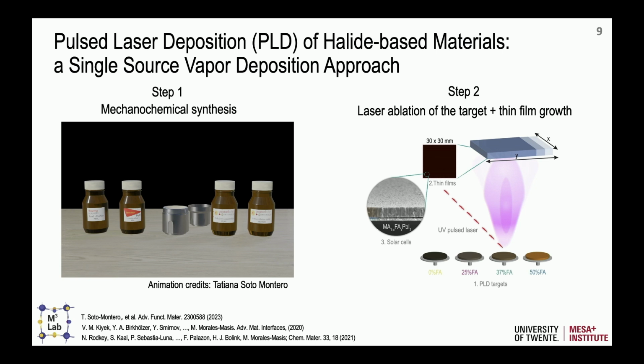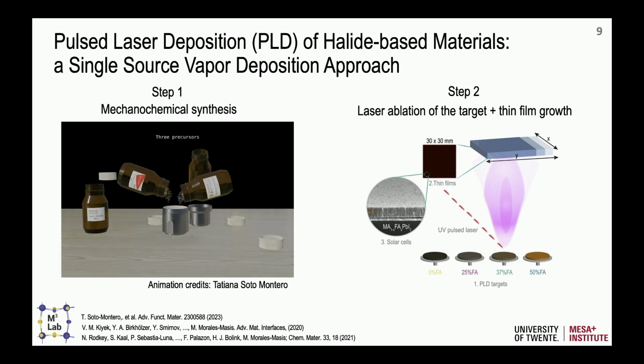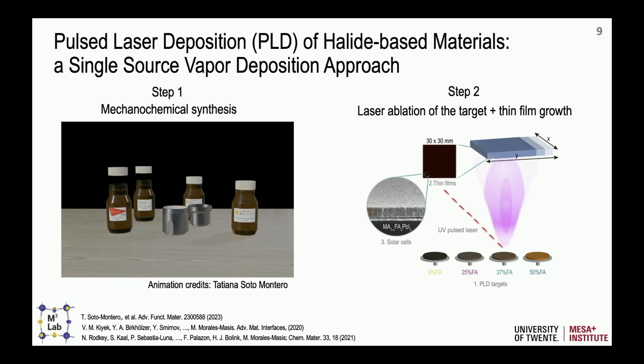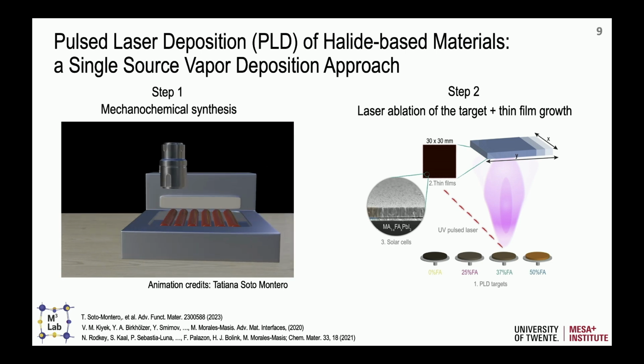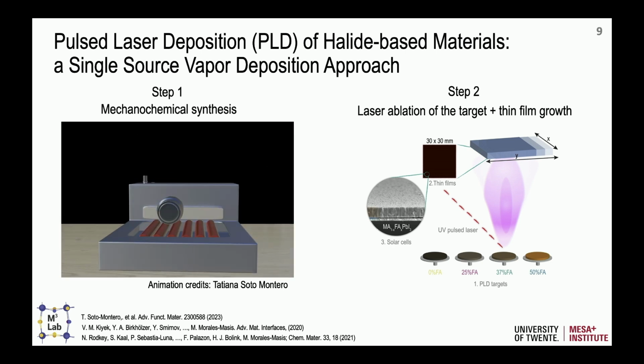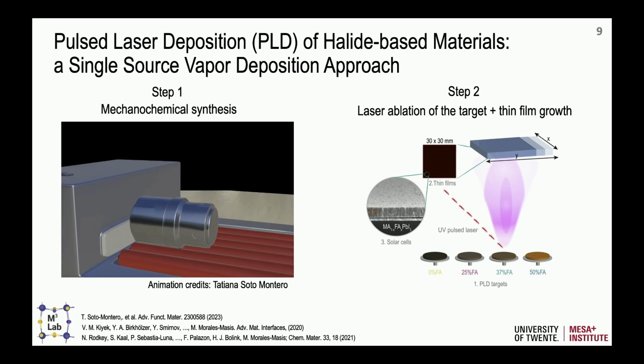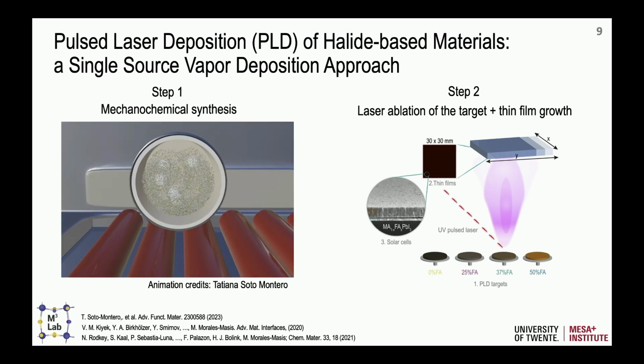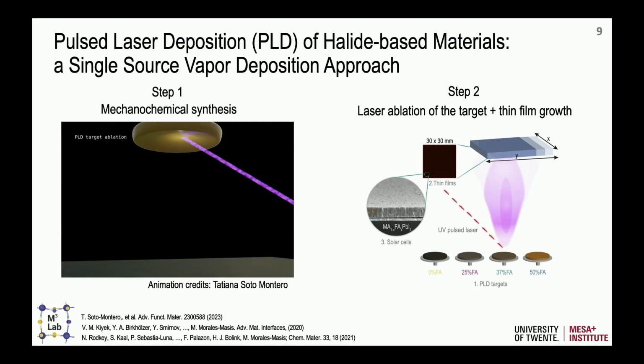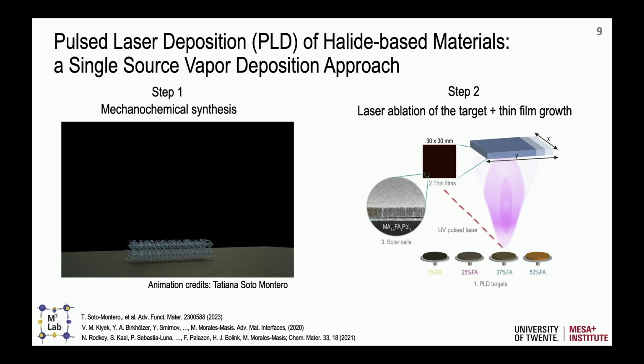So this is a very nice animation from Tatiana that is sitting here, where we basically show that we take the precursors of the perovskites, so the people here doing perovskites can recognize the bottles. We take these powders, and we put them in the mechanochemical synthesis vial. And with zirconia balls, we can basically use mechanosynthesis, where with mechanical forces, the perovskite starts to form. So you can actually see in the animation how we have the precursor salts and how they become the perovskite. And the important thing is we do this because we want to have a material that is very well mixed. When we have this material very well mixed, we can make it into a target, as shown here. And then we use the laser, with quite controlled optics, actually, to ablate the target and then deposit our perovskite film from a single source.